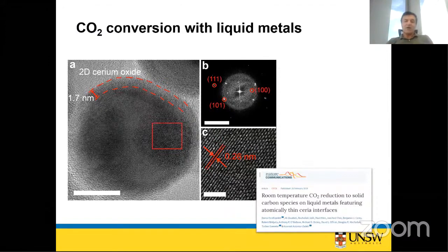What are the applications of these manipulations? Look at one of these very beautiful applications here. We add cerium at 3% to liquid metal, and we supersaturate it because the solubility of cerium in liquid metal is relatively low. It's only 0.1%. Here we added 3%. So what it did, it started forming crystals of cerium in the liquid metal.